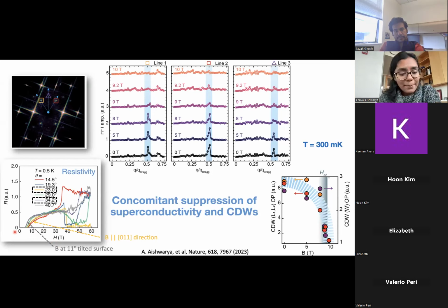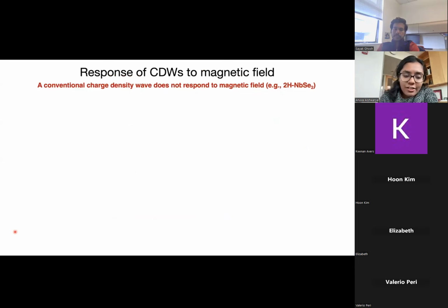So there are 2 aspects to this study that are very strange in terms of what is known about CDWs. One is the directionality, and the other is its relation to superconductivity. So it's not normal for CDWs to respond to magnetic field. For example, take niobium diselenide, where you have a CDW and also the superconductivity. But when you kill superconductivity, you don't see the CDW disappearing.